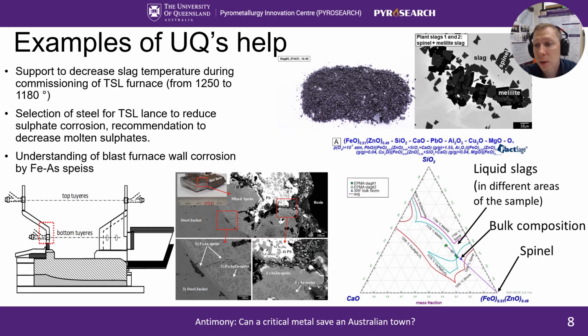Thus, we collaborated with Nyrstar to do an advanced plant sample analysis and phase equilibrium modeling to justify small changes in fluxing, ultimately resulting in decreased temperature of operations to 1180 degrees. This extended the working life of the refractories. Other projects related to hot corrosion included the selection of steel for lances delivering air-oxygen blast into the smelting furnace, and understanding the degradation of steel walls in the blast furnace. The latter was identified as an unusual arsenic-induced mechanism.